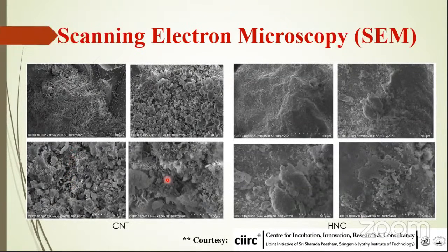These are CNTs, and if you go further, you can see how the surface is jagged. I don't know which area they have magnified here, they have not marked it. So I think there is one here, a few here and a few here, clusters of CNT. Whereas in case of HNC, it's completely incorporated. Even after magnifying on the crack, the distinction between the cement matrix and HNC is not clearly visible, and this is visible in CNT because of the hydrophobic property of the CNT, which keeps it away from water molecules. My only assumption is that HNCs are probably mixing with the water, because of which the matrix is dense and thick, and hence there is no proper differentiation between the compounds.